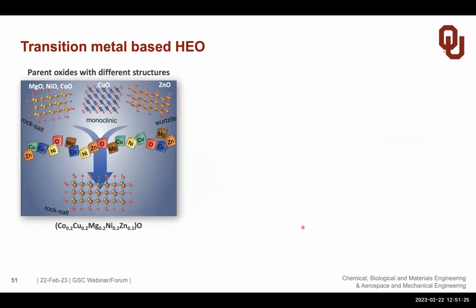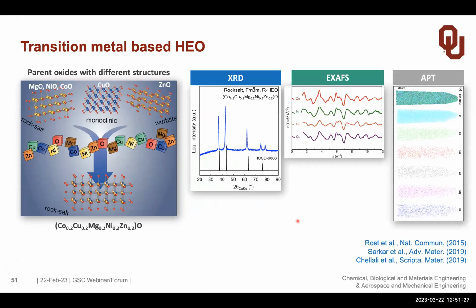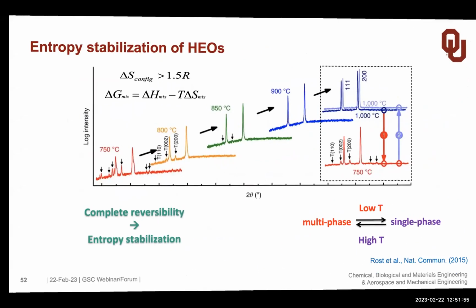This is symbolized here in this schematic. And you can see this in the XRD or in the EXAFS or in the APT, here for the structure, and here also for the elemental distribution of the atoms. They are completely statistically distributed in this lattice of the rock salt structure. So we have phase purity in spite of the complexity, and we have a random and homogeneous cation distribution.